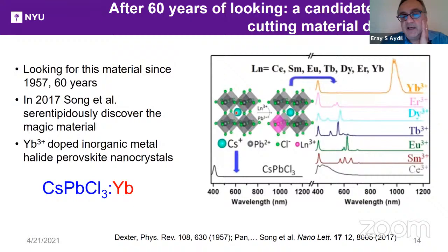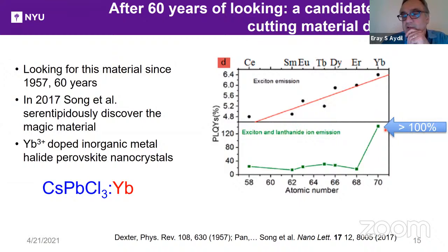And the idea is that the ytterbium, or any of the lanthanides, substitutes into the lead position and dopes it. And then they were looking at the emissions from various rare earths. And so here, for example, is samarium. Here is ytterbium. And the ytterbium emission you see here is very near the band gap of silicon. And what they find is that, yes, most of the lanthanides have some efficiency, but they discover here that ytterbium-doped cesium lead chloride gives a photoluminescence quantum yield in the near infrared of 140%, greater than 100%. So a sure sign of quantum cutting, okay?